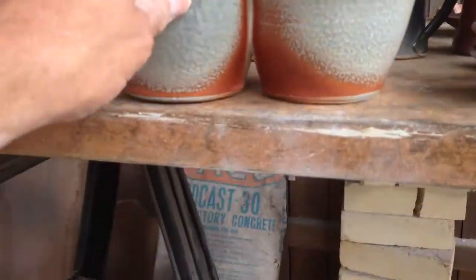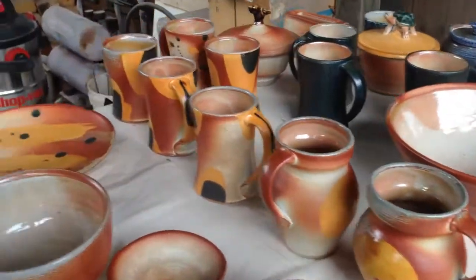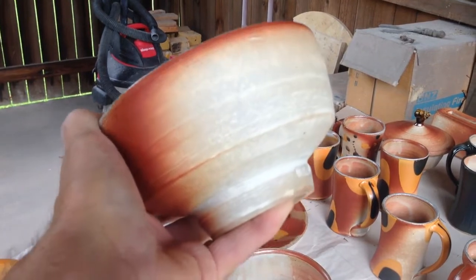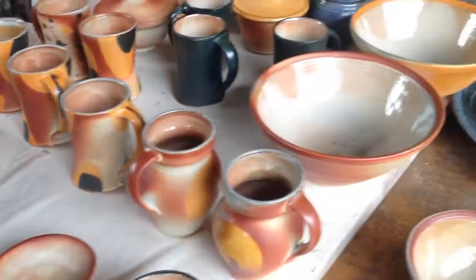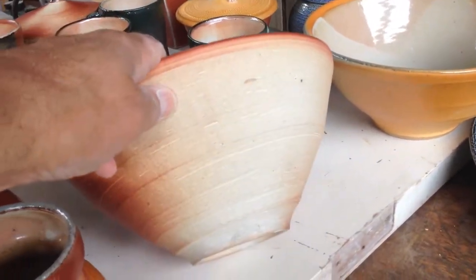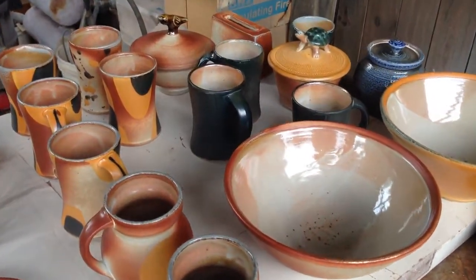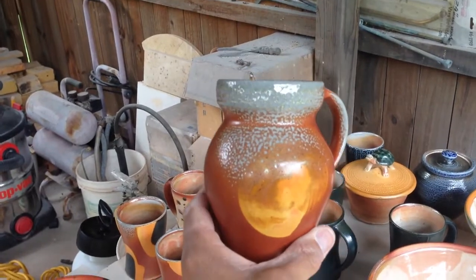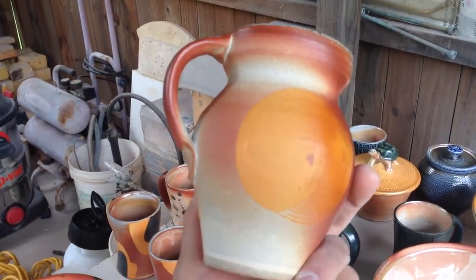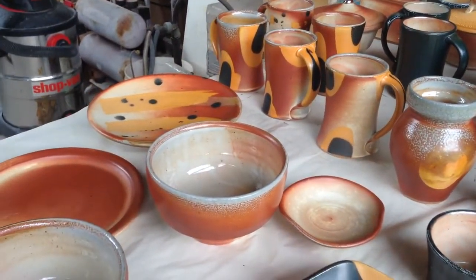The pots facing the front of the kiln got a pretty good hit of soda, but on the back sides it's much drier. Here on this bowl you can see this kale slip — my bower slip that I use a lot — got nothing on this side, but here on this side it's nice. Out of the 120 pots in this kiln, I'm probably going to have maybe 70 or so that get put back through. See this cup — real dry on the back, but the front got some soda. The spraying method I normally use seems to work better for distribution in my kiln.